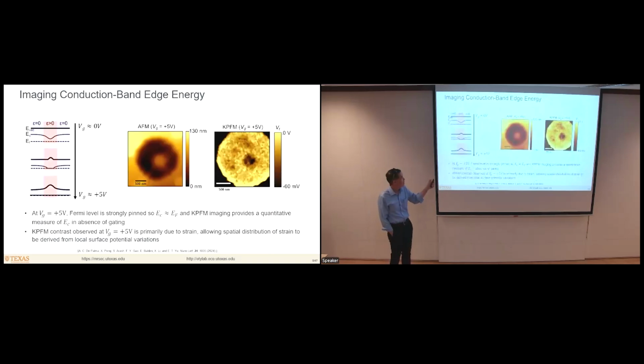Now, one of the implications of this is that if we look at a situation where there is some modulation locally in the energy of the conduction band edge in this material, so this is now looking laterally in the material, and this is the situation that we have when we have localized strain, because the strain induces a lowering of the conduction band edge energy. Then as we apply this backgate voltage, going from 0 volts in this schematic up here to some large positive gate voltage, then the conduction band edge energy is gradually drawn downwards and then eventually gets pinned at the Fermi level. And this happens in such a way that in this strongly pinned situation down here with the large positive gate bias voltage, the local vacuum level is a reflection of the variation in the conduction band edge energy that existed in the absence of the gate bias voltage.